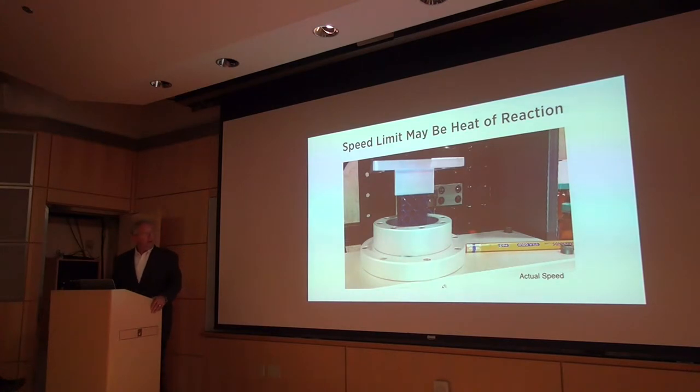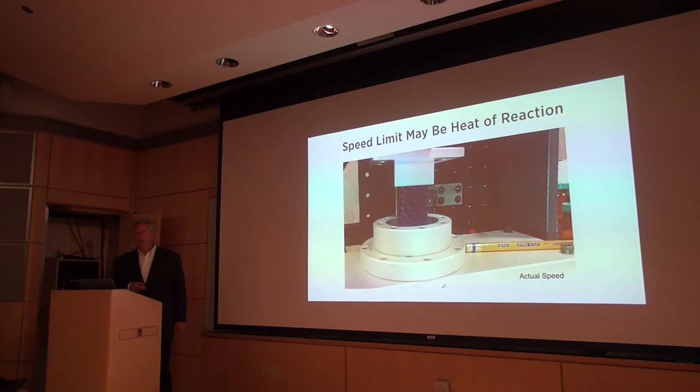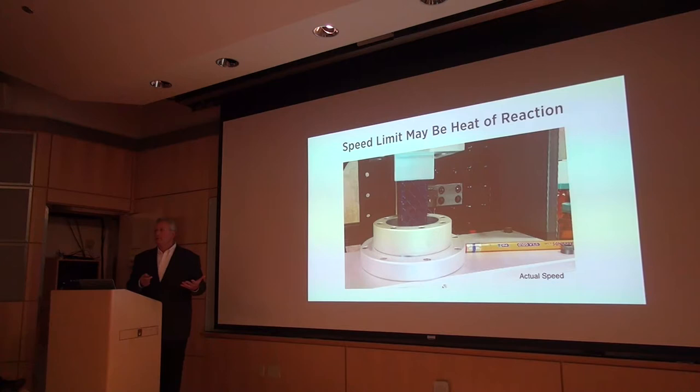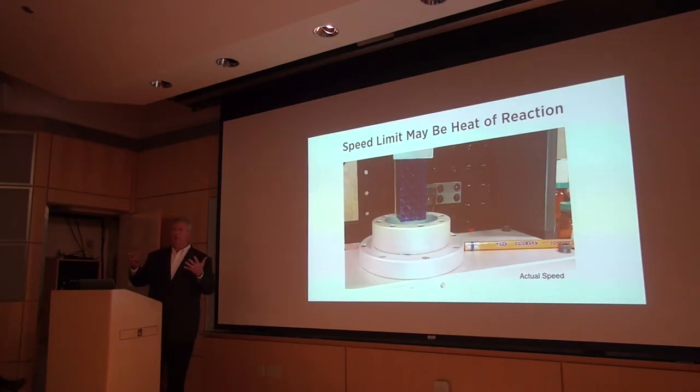This next video is not sped up — it's running in real time. No one will have the patience to show you a real-time video of a 3D printer. If you look carefully, you'll see some wisps of vapor — we're converting a lot of monomer to polymer, and polymerization reactions are exothermic, so this gets really, really hot. These are running at thousands of millimeters per hour. As a chemical engineer, I'm pretty excited because we now have heat transfer issues to worry about — we've taken 3D printers into that kind of regime.